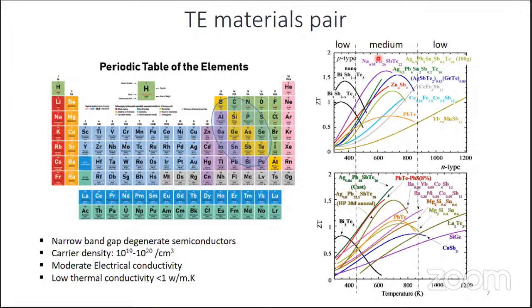Then when it comes to the medium temperature, that is 200 to 600, a lot of materials, the lead telluride, and then skutterudite, and zinc antimonide. In fact, we tried all these materials. These all show very good performance. But the point here, I'll explain, is that it is an extremely poor material in terms of thermal stability. So that is why, in spite of excellent properties, so far no commercial module made up of lead telluride or zinc antimonide is available in the market.